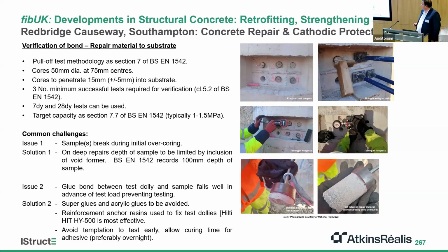Now, one of the challenges that we've seen on a lot of jobs is the contractor tries to do the sampling at an overlay which is too thick. And when they've tried to core the sample locations ready for the pull-off test, what they're finding is that the core is breaking while they're drilling the core out. So one of the techniques, if you get asked to do a bond test, is to try and minimize the thickness of the test sample so that when you core it ready to do the pull-off test, you're not going to fail it during coring.